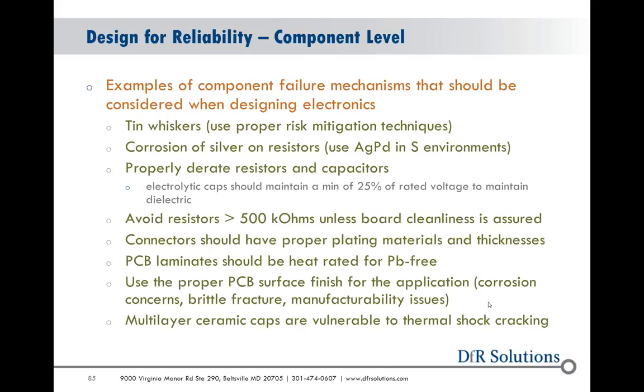Connectors — make sure they have proper plating materials. If using gold, how thick is it? How many insertion-withdrawal cycles? If tin, do you have fretting concerns due to micro-vibration? PCB laminates — are they rated properly especially for lead-free environments, and are you using the right surface finishes? The right one depends on the application, as there's potential for corrosion, brittle fracture, and manufacturability issues. Multi-layer ceramic caps are vulnerable to mechanical fracture near board edges or thermal shock cracking if heated or cooled too quickly.